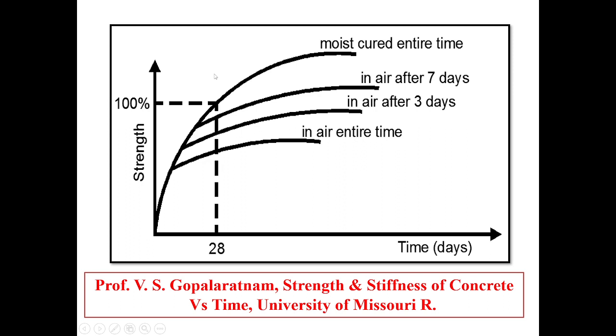So here it is 28 days. At 28 days, here it is 100% strength when the concrete is moist cured the entire time. That means the concrete is cured all the time, so they have taken this benchmark as 100%. Now the second curve, one curve below, shows concrete in air after 7 days. That means the concrete is cured only for 7 days and then exposed to the air and then tested at 28 days. So the strength has reduced.